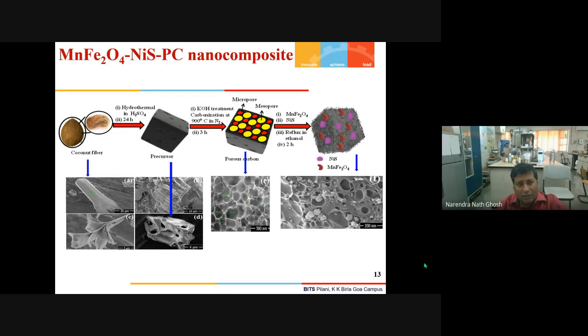Here, I'm telling you about a composite where, in porous carbon, we have decorated manganese ferrite and nickel sulfide. This is coconut. We collected the coconut fiber. When we examine this coconut fiber by scanning electron microscopy, it looks like this, and you can see that it has a layered structure. Then we treat it hydrothermally with sulfuric acid for 24 hours, and we see that the layered structure becomes delaminated and some pores are generated. We call it the precursor. Then we treat this precursor with solid KOH at a high temperature of around 900 degrees Celsius under the flow of nitrogen, and we got this kind of porous carbon structure.